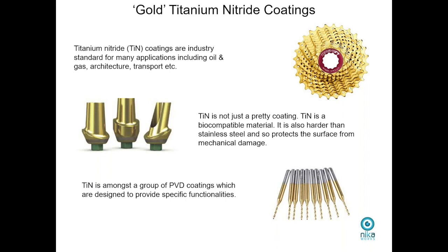Well, if you ever go to, again, Homebase in the UK, Home Depot in North America, look at some drill bits, you'll see that most of them nowadays have got a lovely gold coating. That gold coating is not gold because that would wear off. The gold coloration comes from combining titanium and nitrogen in our sputter process. Titanium nitride comes out a beautiful gold color, and that's used as a protective coating for many surfaces because its micro hardness is greater than stainless steel. So it gives some scratch resistance and reduced coefficient of friction if the conditions are correct.